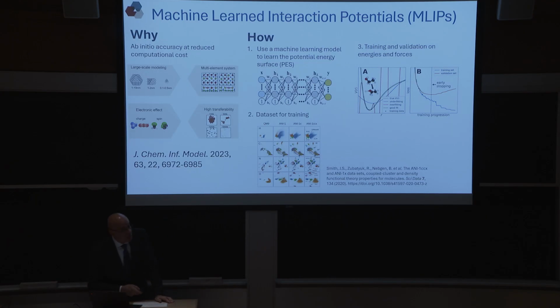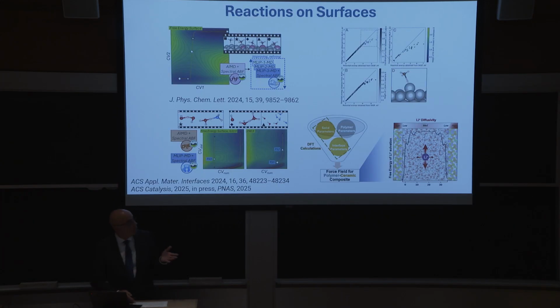So we've been experimenting with these methods and apply them to a number of systems. For example, chemical reactions on catalysts, where now you can do elevated temperatures, you can take into account entropy, we've been looking at water autoionization or lithium transport in batteries at interfaces. And in all of these cases, it seems to work. One of the challenges here is that in many instances, these force fields are unstable. And the reason they're unstable is that during a simple simulation, you don't expose them to these artificial, difficult conditions that would arise when you're about to break a bond, for example. So you need to come up with strategies that allow you to explore those regions to train the force field. And that's what we've been doing.